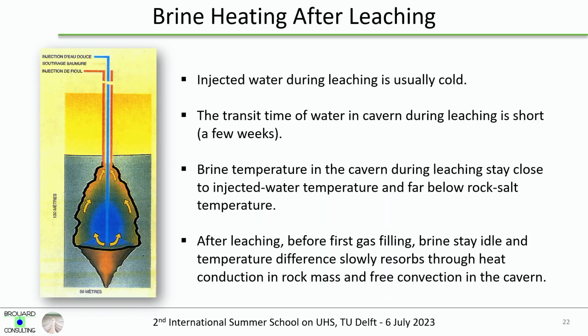Some information about the thermodynamics. You have to remember that initially when you create a cavern, you inject water that comes from the ground, and most of the time the temperature of the water is less than the temperature of the rock. So it means that at the end of the mining, the temperature of the brine in the cavern is much less than the rock, and so you have some heating of the brine in the long term. And after the leaching, before the first gas filling, you have some resorption of the difference in temperature. It's mainly due to the convection in the caverns.